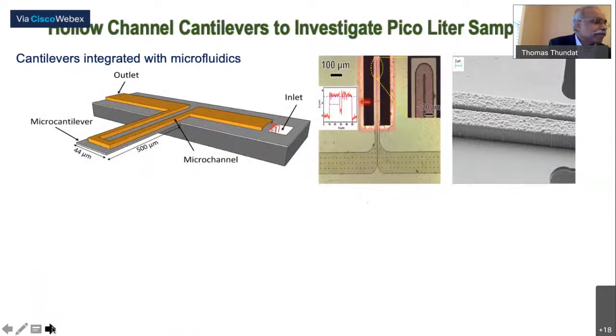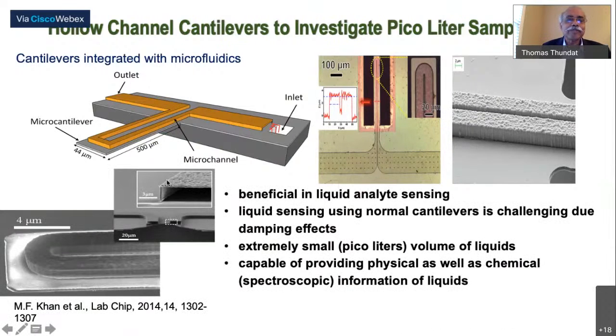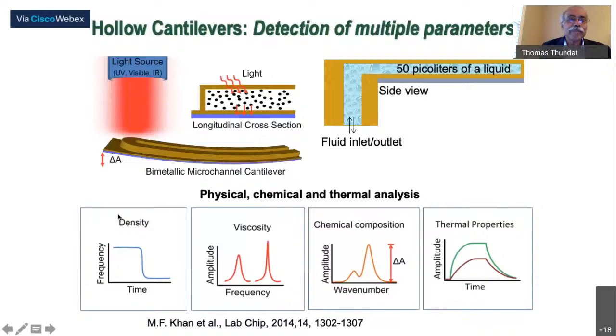And so people have asked me, oh, what about, for example, liquids? Can we do this in liquid? Again, we have a cantilever, and we can have a microfluidic channel developed on it. These are the pictures showing the hollow channel on the top of the cantilever. It's around 50 picoliters or so, and you can actually get the spectrum. For example, this is the cantilever, the channel. You can measure the density of the liquid by vibrating it in time, and since the volume is known, you can calculate the density from the resonance frequency change.